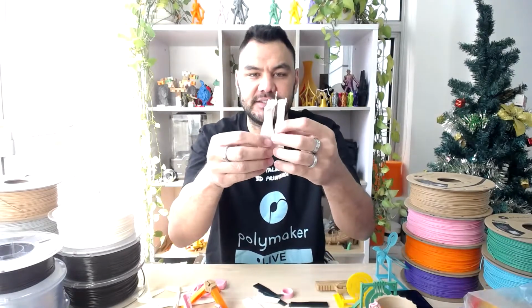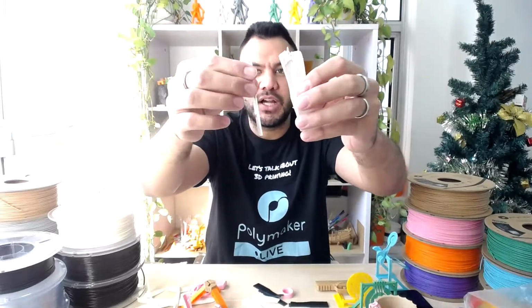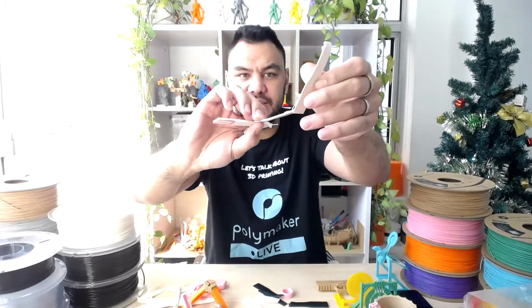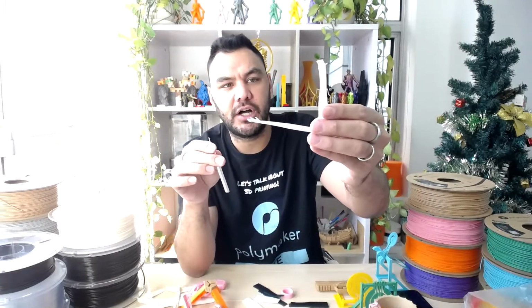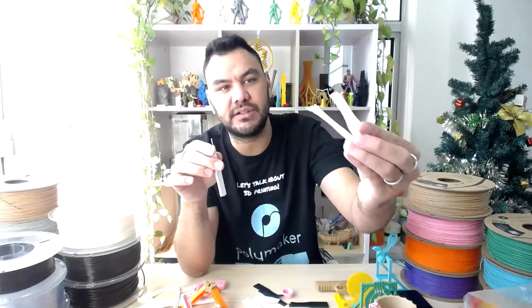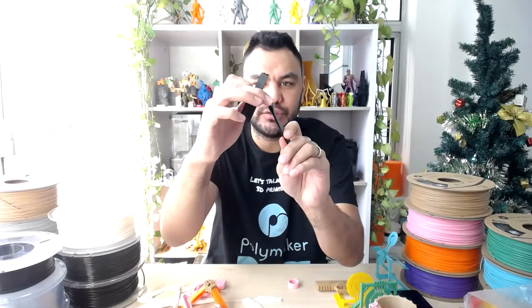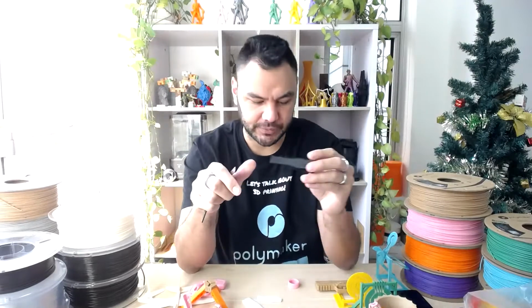And then we have our PCABS that was very difficult to break. It requires a lot of bending, a lot of spinning, a lot of pulling, but it also delaminated all the way. So I guess this material might be good for small parts if you're printing on a desktop printer. If you're printing bigger parts, then you will require a heated chamber. And then our PCPBT, which broke almost the same as Polymax PC, but it started to delaminate also. I'm pretty sure I can also remove that part here. Yeah, you see? So it is very important to print at high temperature, around 300 degrees, and with a heated chamber. So not a material for all desktop printers. Okay, so that's for the polycarbonate destruction.